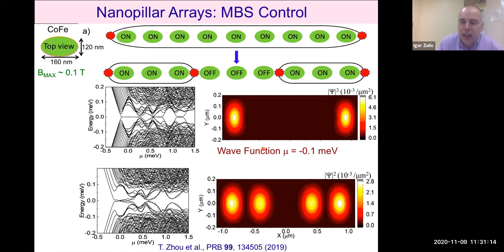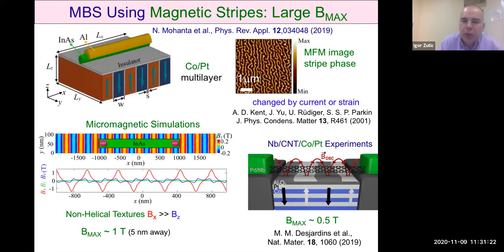This little bit far-fetched idea now has been brought closer to reality, because similar to our studies of how magnetic textures can support Majorana states, and again with more micromagnetic simulations, we've seen now that this induced synthetic spin orbit coupling was recently experimentally demonstrated in Paris. So a carbon nanotube next to two niobium regions and then a cobalt platinum multilayer was supporting Majorana fermions. So basically, at least in principle, one can use this combination of magnetic and superconducting proximity effects and the role of inhomogeneous magnetic textures to design very exotic superconducting states.